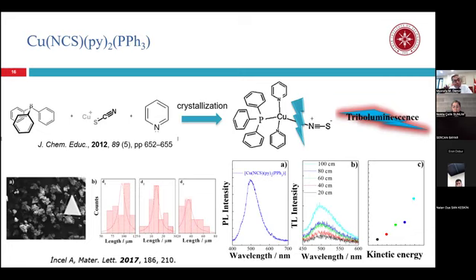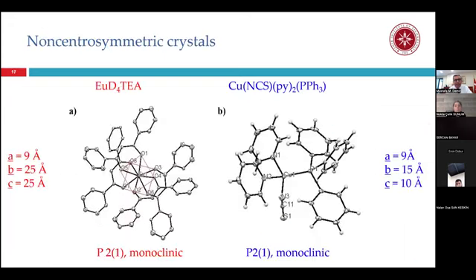For the blue emitting copper isothiocyanate bipyridine triphenylphosphine, we have a similar story. The synthesis is known and we carry it out with undergraduate students in our lab. The key point for both systems for triboluminescence applications is as follows. In order to have emission, the crystals should be non-centrosymmetric. That means when a mechanical force is applied and the crystal breaks, you need oppositely charged new surfaces, so it gives you this opportunity. Both crystals are monoclinic, with different unit cell dimensions.